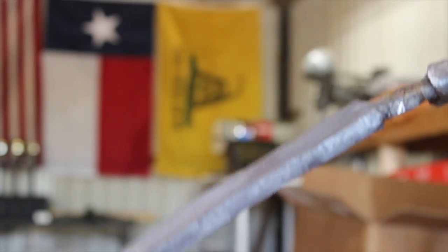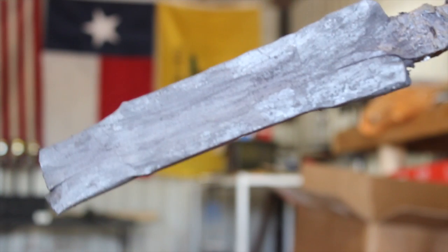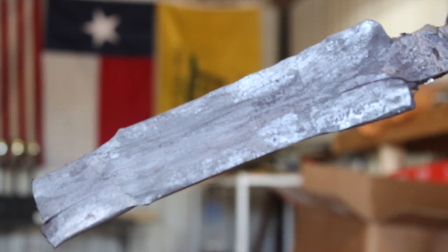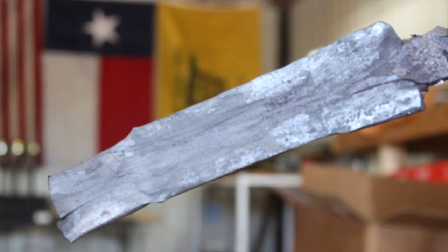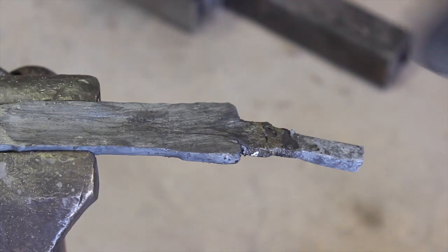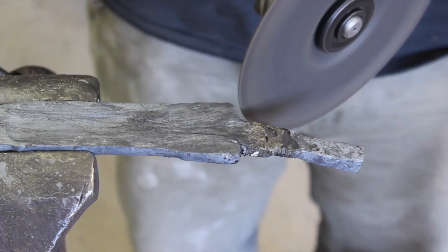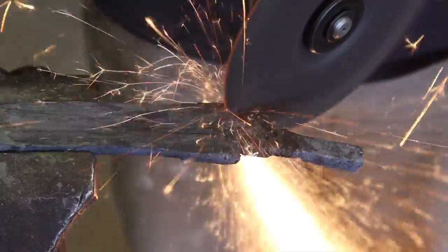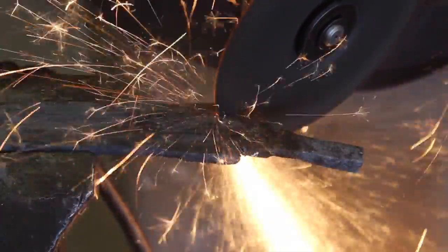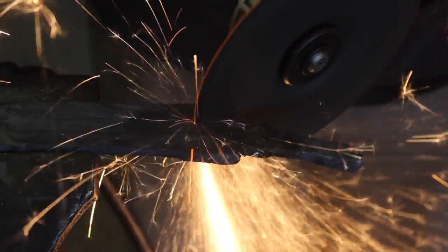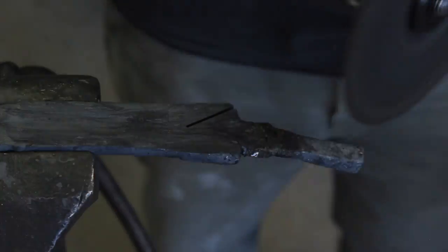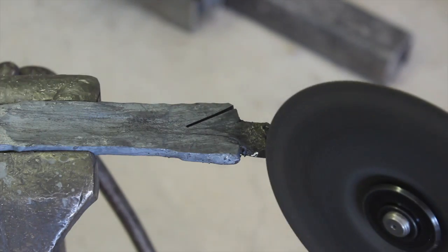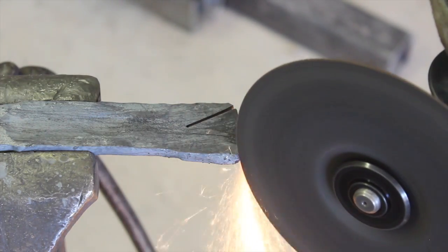So you can see I got some spots where the weld did not work, and that's not surprising. The tack welds that you hold your billet together with, even on your typical Damascus or pattern welded billet, it just doesn't weld right there. And now it's stretched out, so it looks like a lot longer spot that didn't weld. I could have probably paid a little closer attention to that, but anyway, we'll work with it.